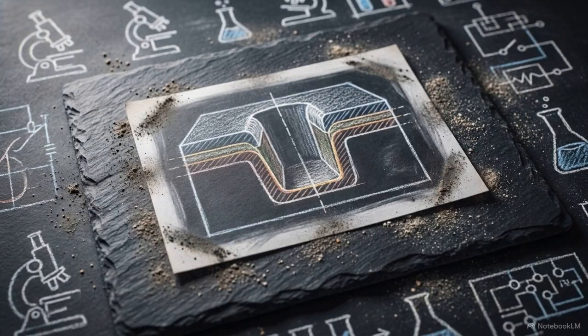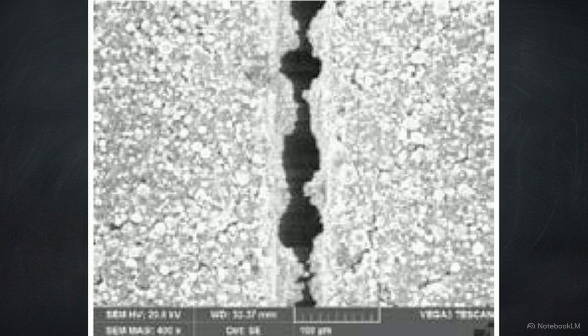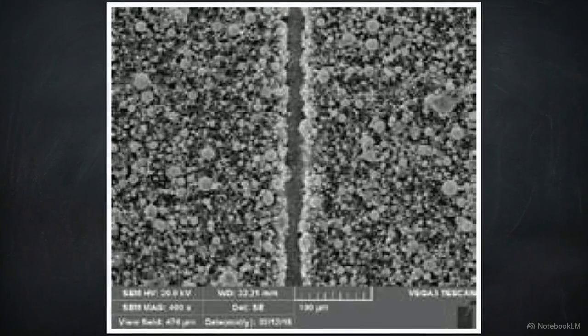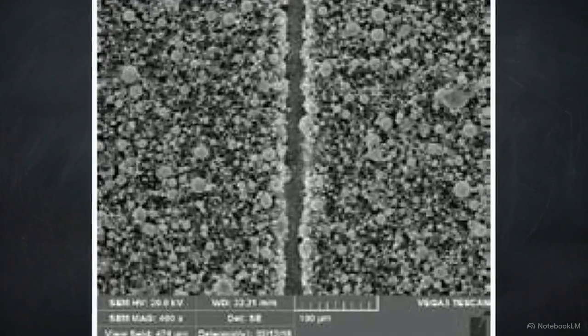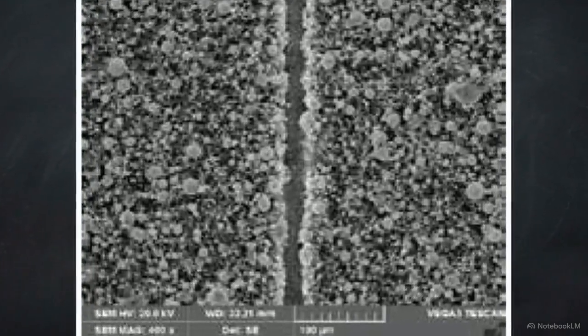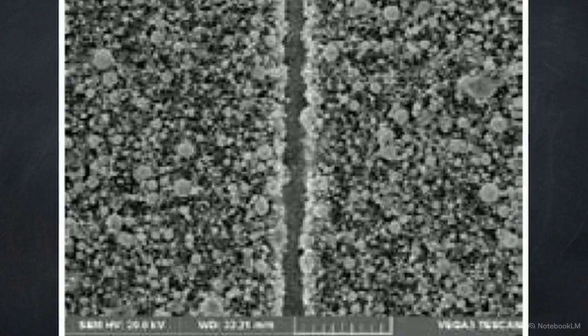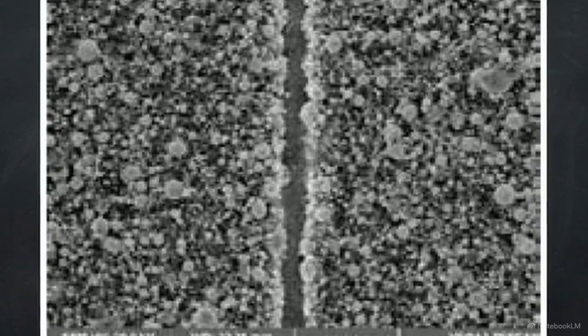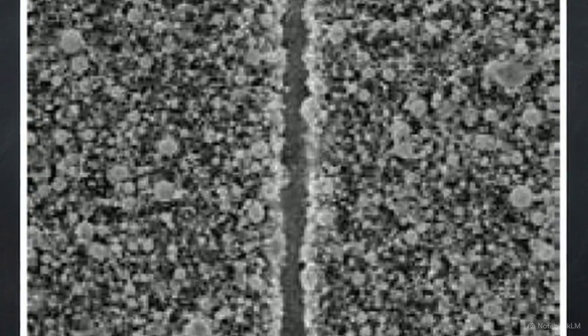We can observe the physical evidence of these thermal dynamics by examining the actual cut-edge morphologies under an electron microscope. There is a specific thermodynamic window where the laser forms perfectly uniform kerf and top widths. Researchers identify this as the proper cutting region. If the volume energy exceeds the electrode's ability to diffuse the heat, the cut hits the excessive cutting failure state. The aluminum current collector melts unevenly, re-solidifying into jagged, irregular edges.